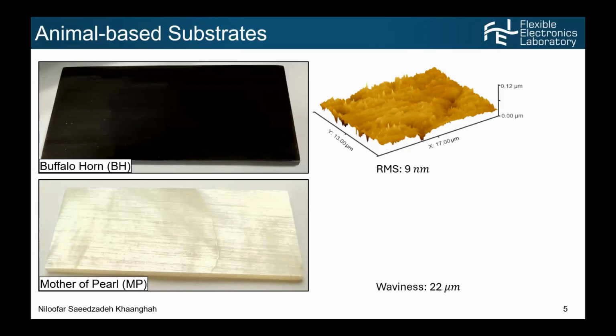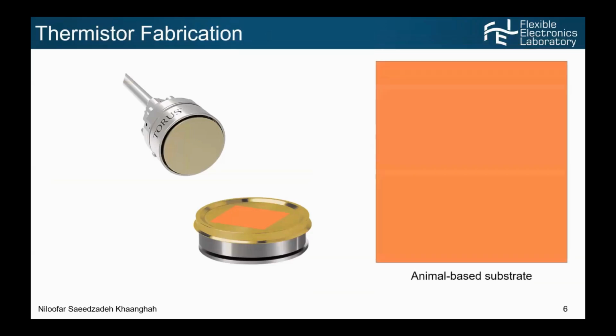The surface of the buffalo horn was polished by the manufacturer. As you see, the AFM measurement shows the surface roughness here with maximum vertical roughness of 0.12 micrometer and a root mean square of 9 nanometer. However, the mother of pearl has a smoother surface with some horizontal waviness that the confocal microscope showed a maximum height of 22 micrometer. So what I did was I used this substrate to fabricate thermistors on top. And this is the process.